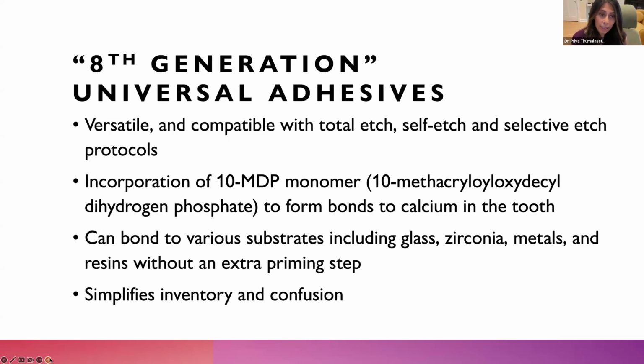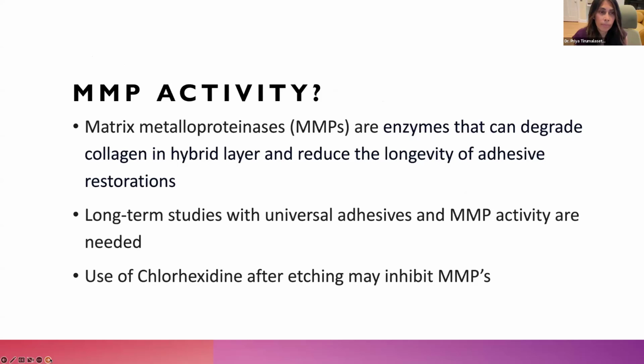The great thing is that this really simplifies the inventory, and of course, the confusion that you may have when you're trying to figure out which substrates to use for which particular material. One key point is that MMPs, matrix metalloproteinases, are enzymes that can, in the hybrid layer, degrade the collagen, and then long-term could affect the adhesion of the restoration. So we need more studies with universal adhesives and MMP activities. One tip again is if you have chlorhexidine in the office, if you use that after etching, it could inhibit the MMPs.